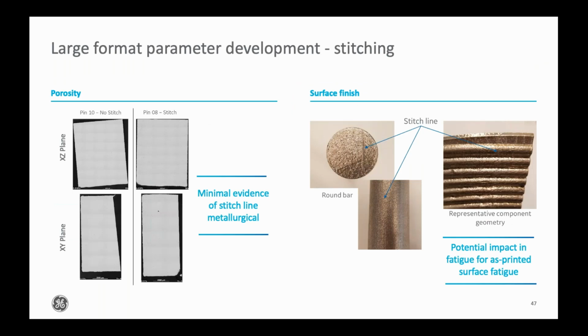And as I mentioned earlier, with Atlas, there's the idea of stitching in order to generate those very large parts. It's maybe hard to tell, but on the very left is what we would say is the no stitch area, representative of full material in a non-stitched region, and then on the right would be a stitch region. Part of the reason to show those is you're not seeing a very drastic patterning of porosity that one may be concerned about when you're trying to meet up two interfaces.